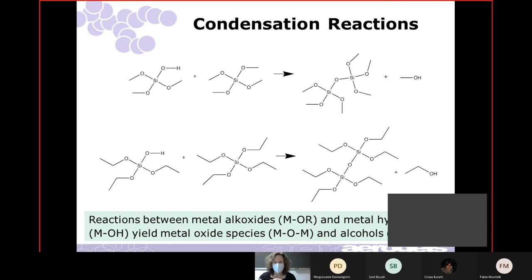And so both of those reactions will be happening, and they'll be happening on the multiple branches of the various silica species until we make some small clusters of silica-containing particles, at which point we will have a colloidal solution, or the sol. As the sol particles continue to react with each other via condensation reactions, we make the gel. And so this takes a little bit of time, depending on how much catalyst is used. The typical recipes that we use under room conditions, gelation would occur within about an hour, maybe 2 hours, depending on the amount of catalyst that's used.